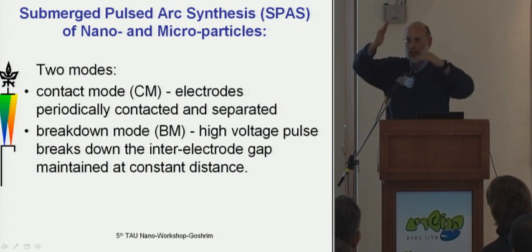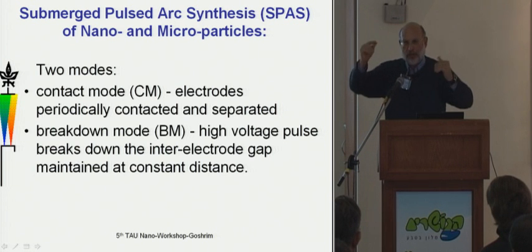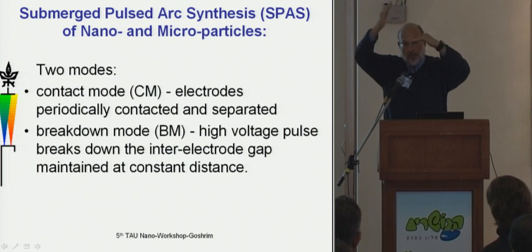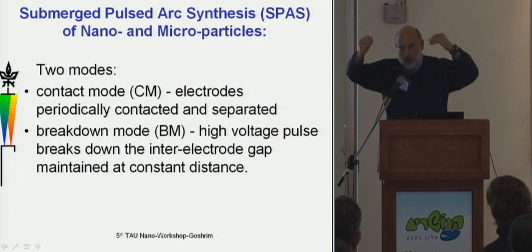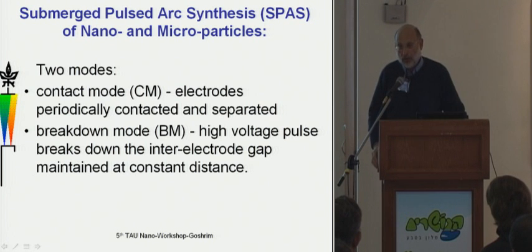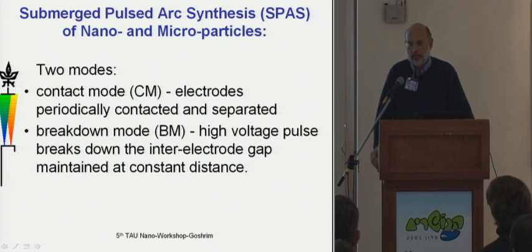And with every contact, there's a capacitor that's charged. When you make contact, current starts to flow, and the contacts bounce. When they bounce apart, it draws an arc. An arc is a low voltage, high current discharge, and that also produces a plasma. The nice thing about this is that it's cheap.